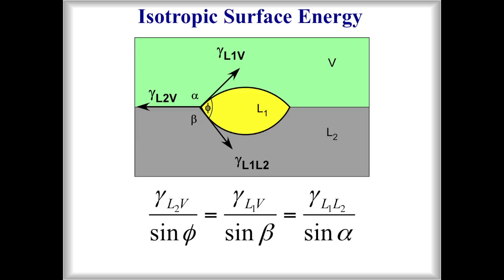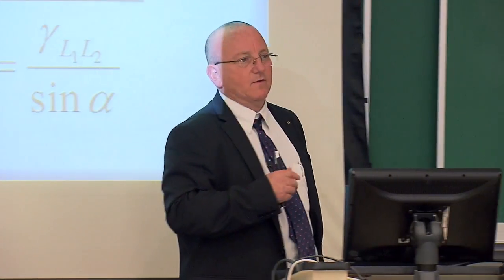How can we do this really? Well, here's an example, again, isotropic, and only liquids. So we have a vapor phase, we have a yellow liquid, and we have this gray liquid down here. And if we reach equilibrium, we'd have this lenticular shape. And now I can define the three dihedral angles that are formed. And I can look at the interface energies, and I can write the von Neumann equation, or the sine equation, some people call this. And if I know one surface energy, then I can work my way around and work out all the other surface energies of the system. This is fine. It works for the isotropic case for liquids. And it's really, really important. There's a lot of work on liquids that that's really useful for.